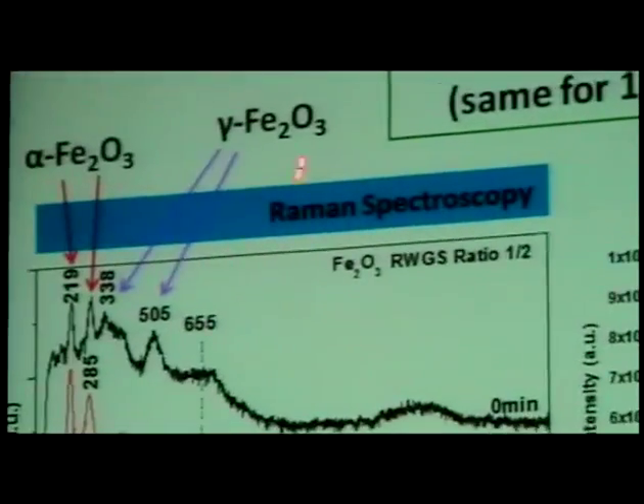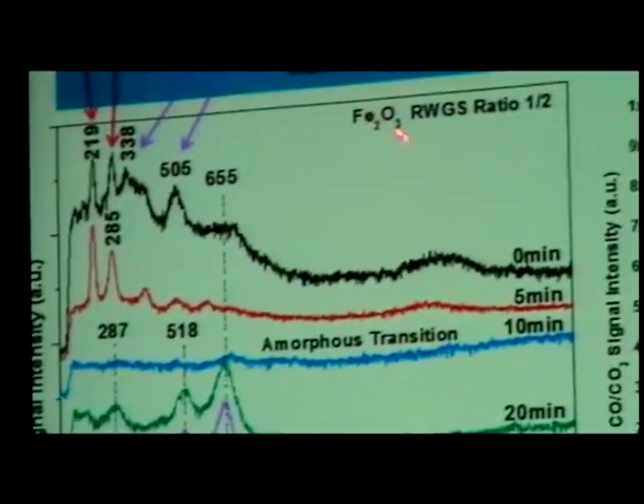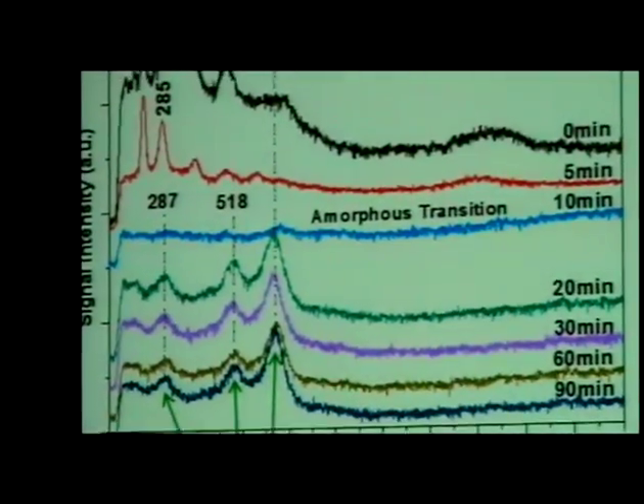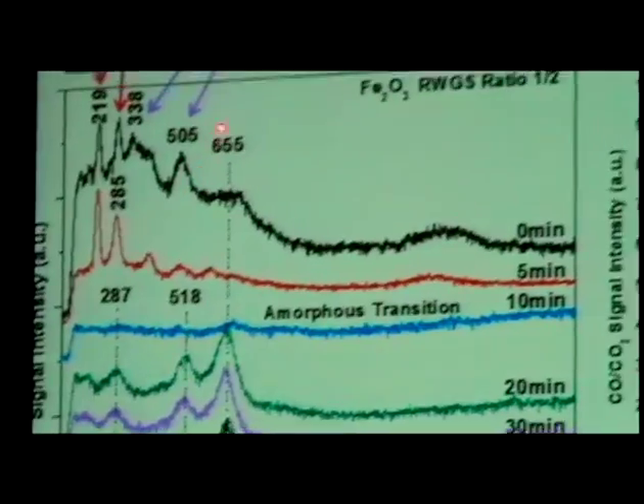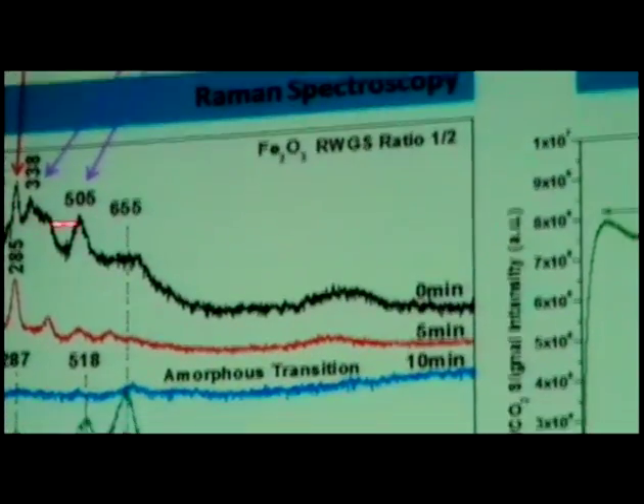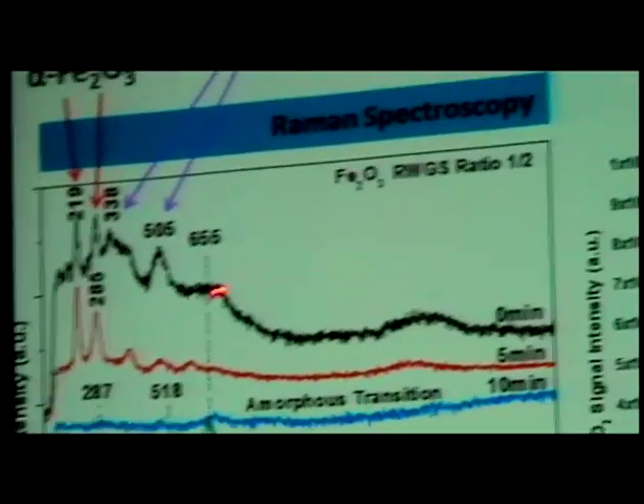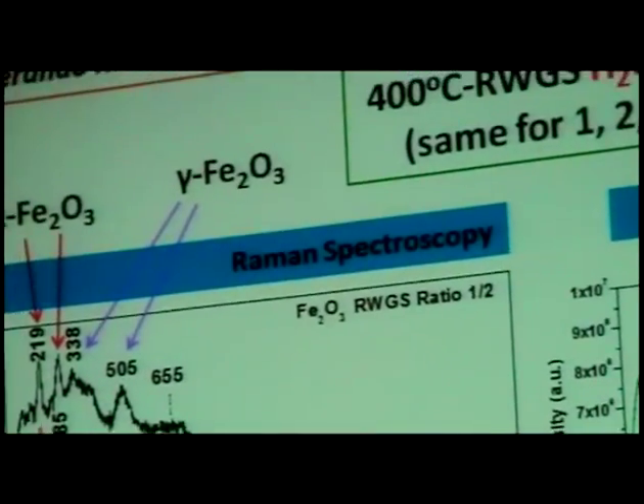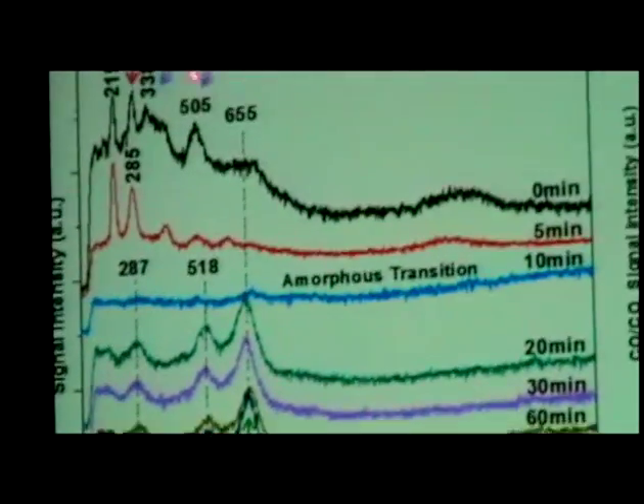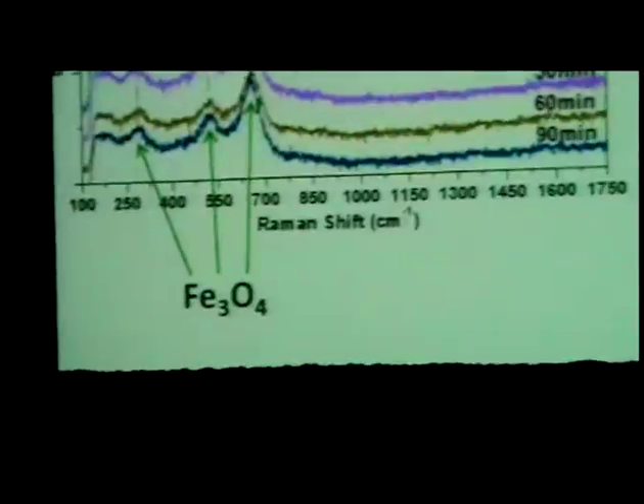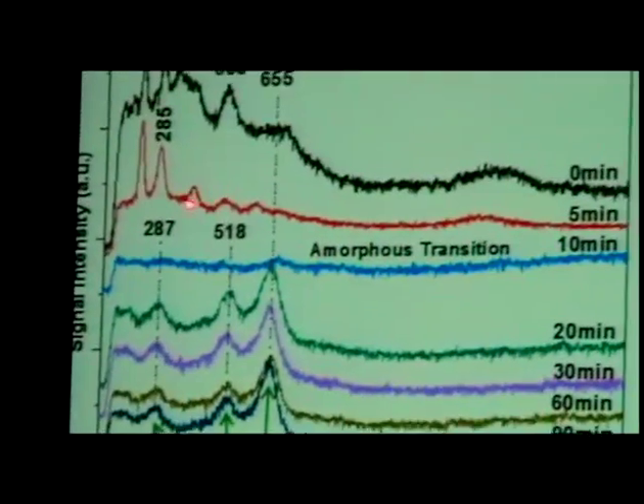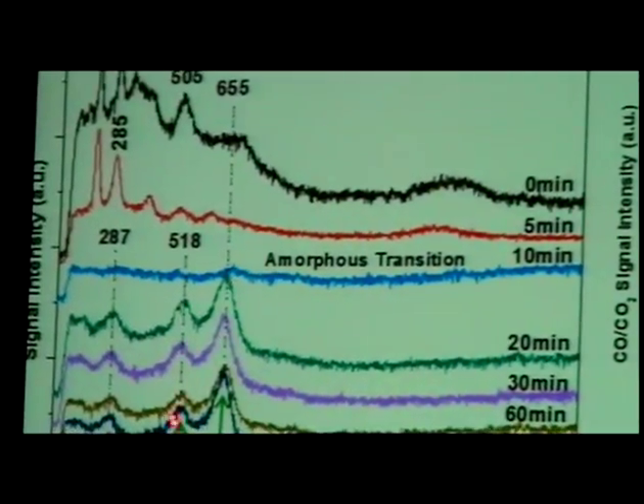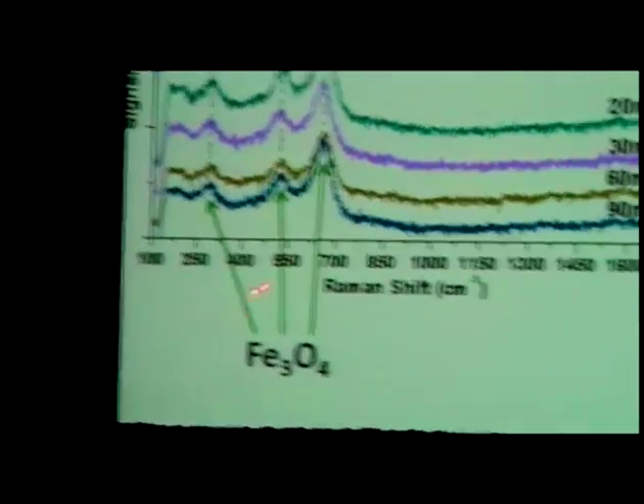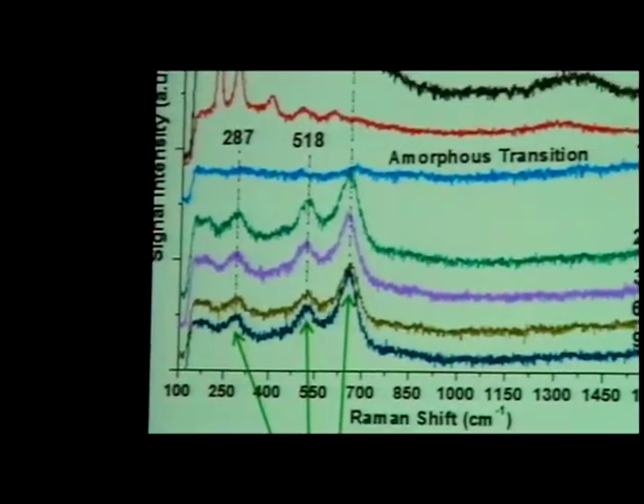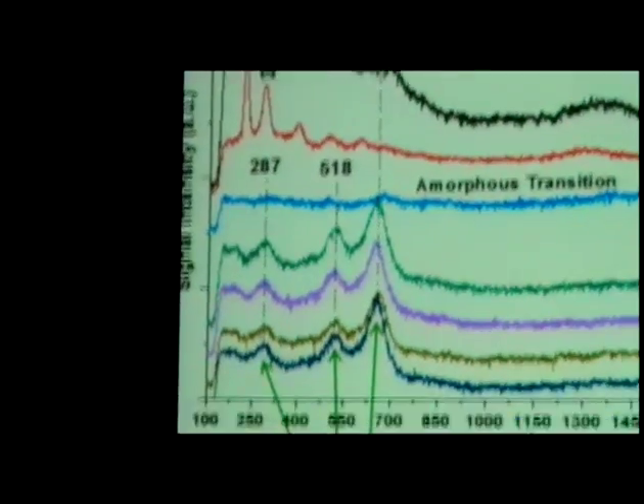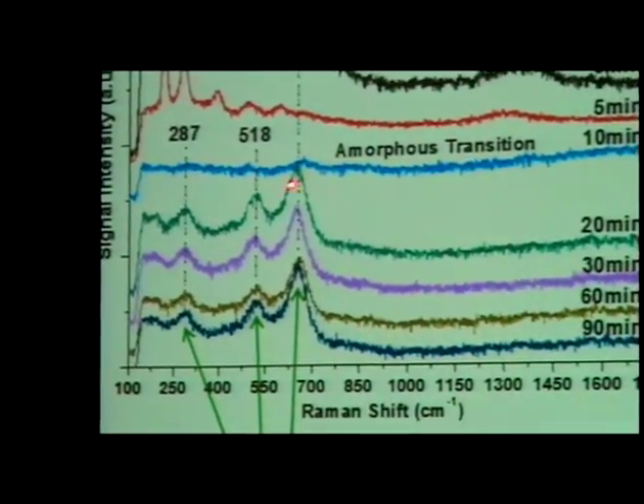So you see these peaks here, and it turns out that the original iron oxide under these conditions is both the alpha Fe2O3 and the gamma Fe2O3. They have very distinct signature vibrations. As we start running the water gas shift, note that after about 10 minutes the bands are gone. So either the material totally reduced or it's transforming. And it transformed because after the loss of the Fe2O3 bands, what appears now is Fe3O4. All these new bands that we see are due to magnetite. So indeed, the iron oxide becomes magnetite under the water gas shift reaction conditions.